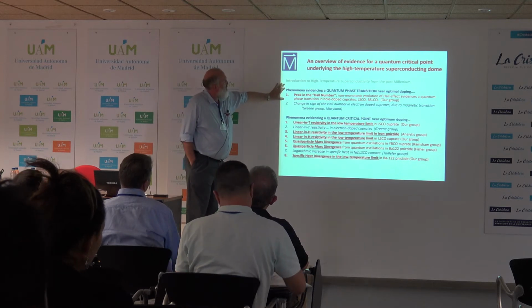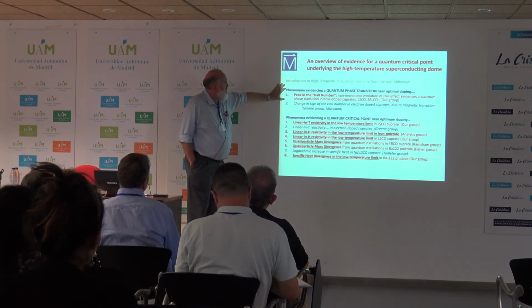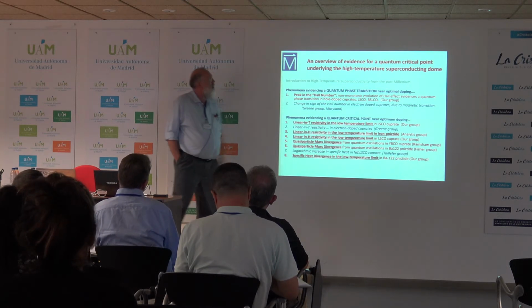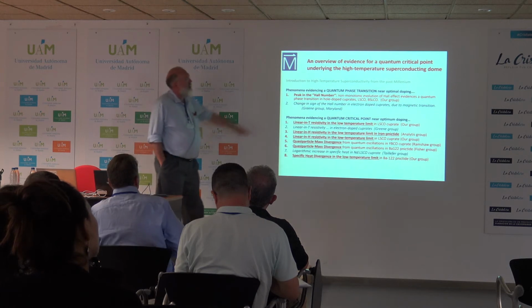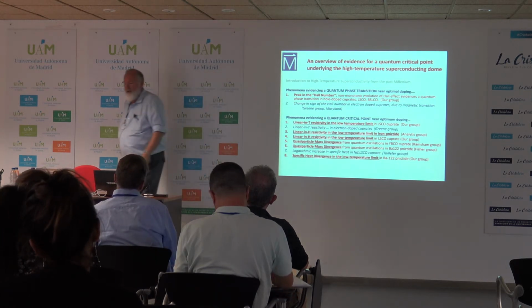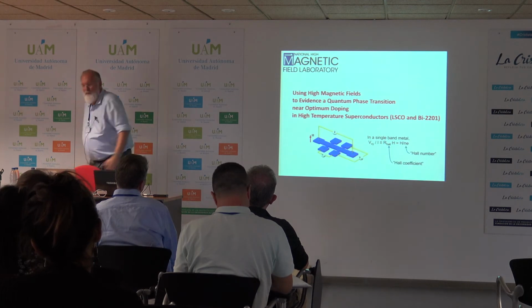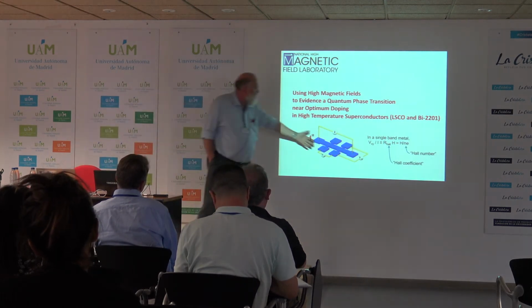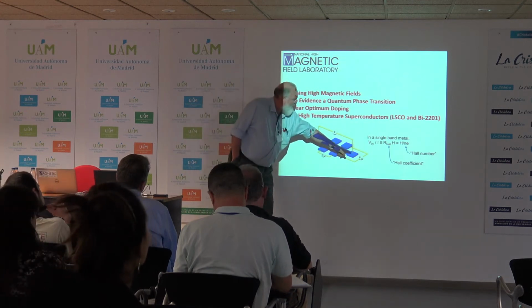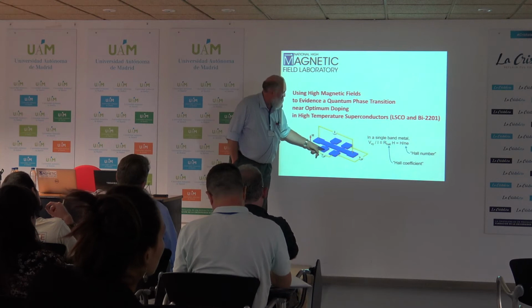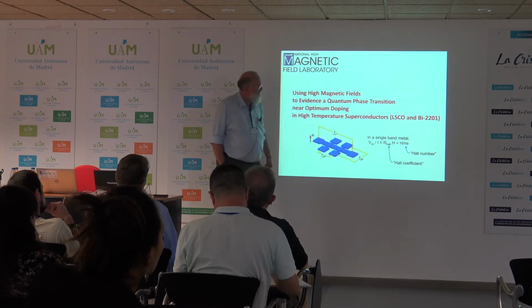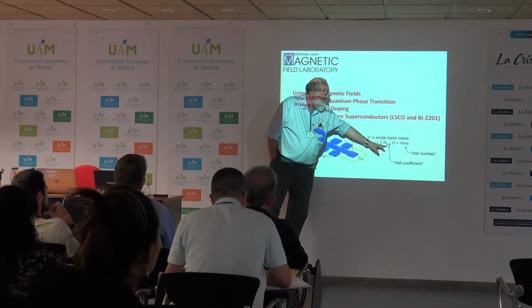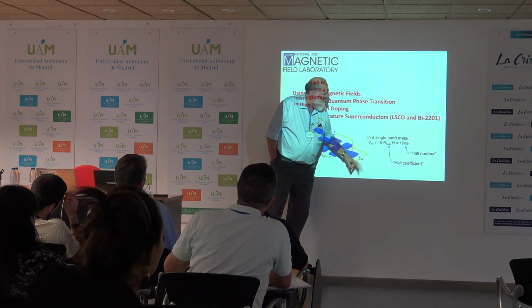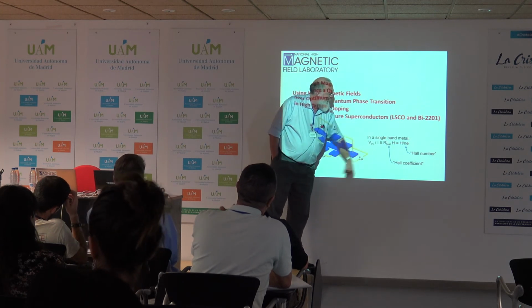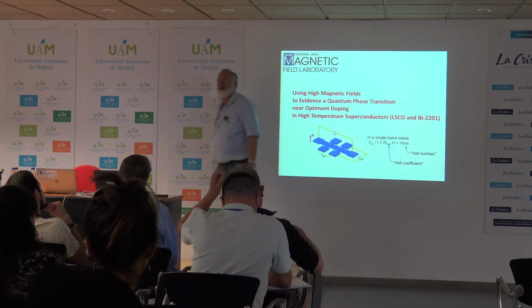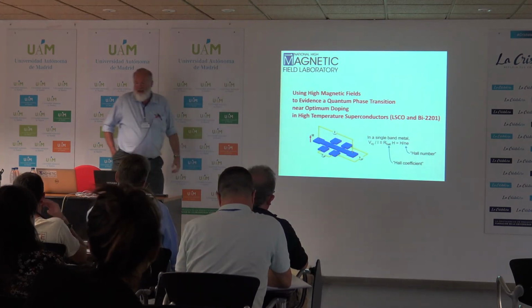So I'll now go into the first high field data, and the physical result is the observation of a peak in the Hall number, a non-monotonic evolution of the Hall effect that evidences a quantum phase transition in hole-doped cuprates. So, as we saw earlier, you make a two-dimensional Hall structure, you apply a current down the spine, you measure either the longitudinal resistivity or the transverse resistivity. I'll use the same terminology. Our Hall coefficient is just the slope of the Hall voltage that is linear in H, and then in a single band metal, that's equal to 1 over NE, where N is the number of carriers.